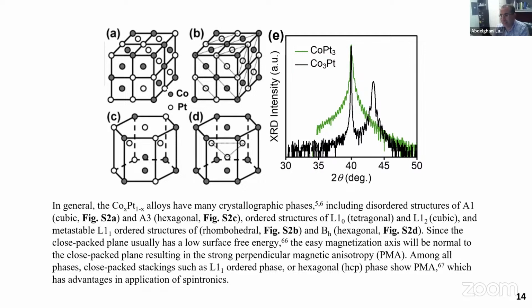There is no significant ordering, or I don't think so. I would say if you look at the XRD peaks, you see some order, you see peaks there. But this 40 degree 2 theta, which ordering does it correspond to? I don't have the angle. But here we see cubic and tetragonal, so that's like a composite of different ordered crystal structures.